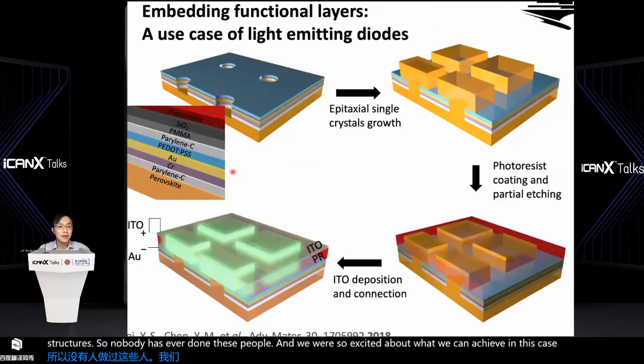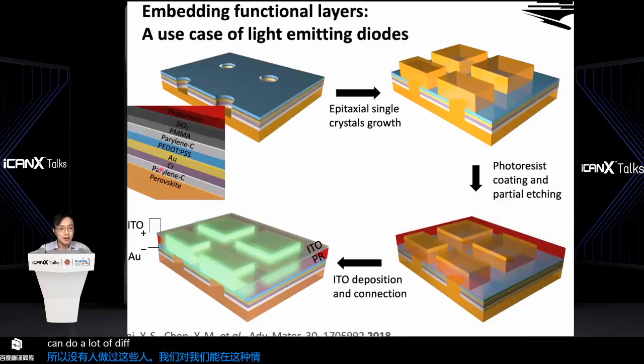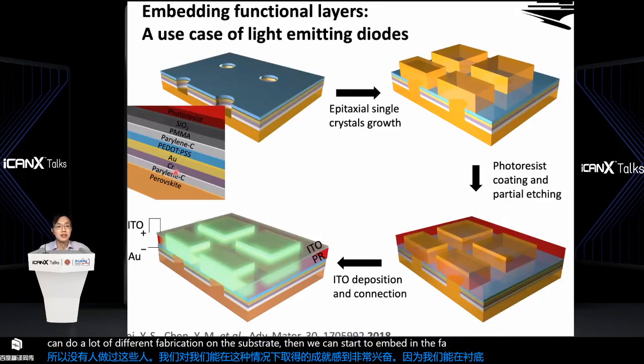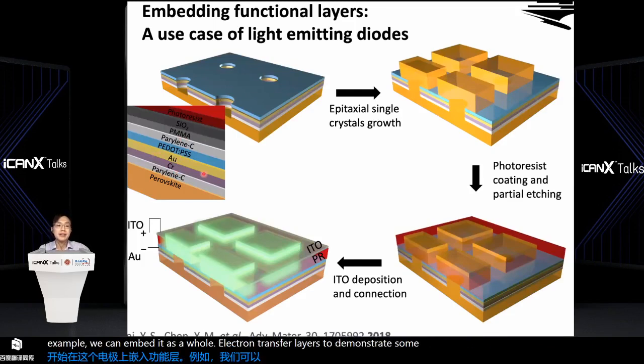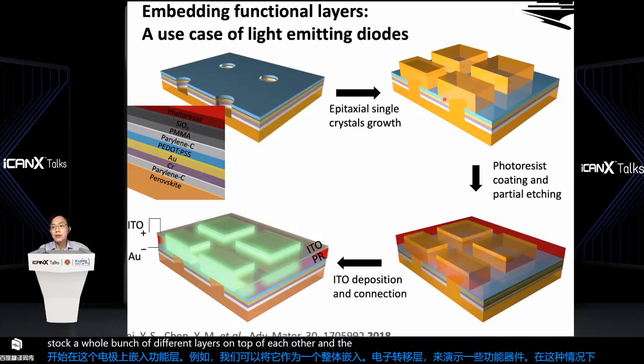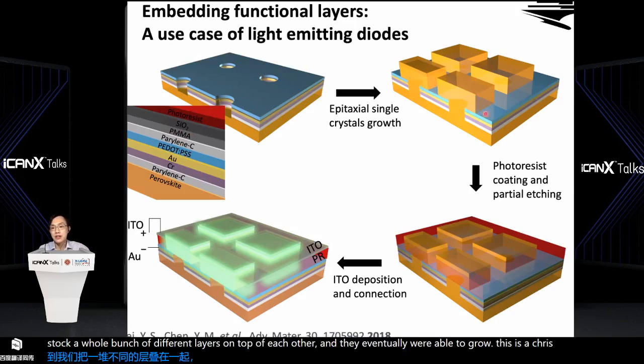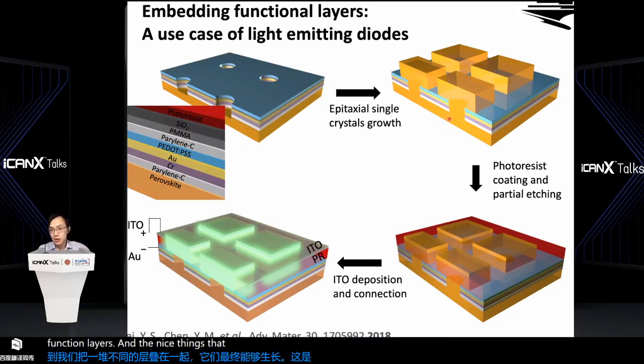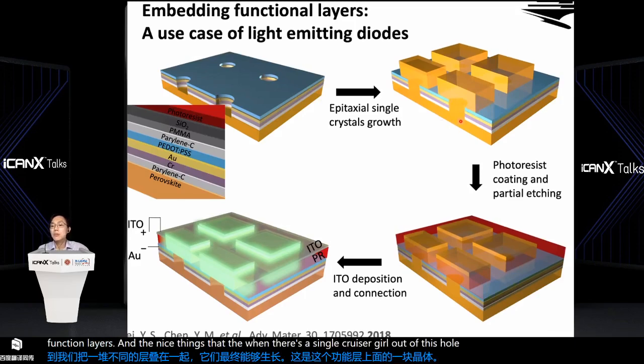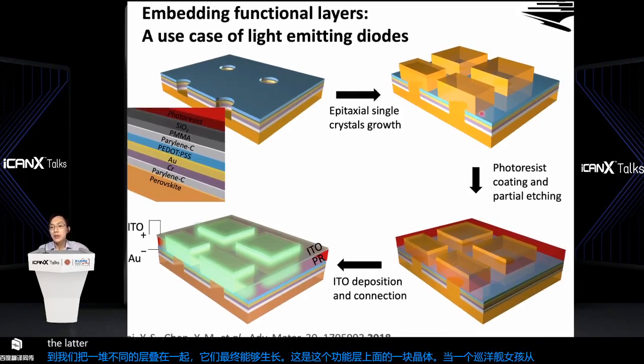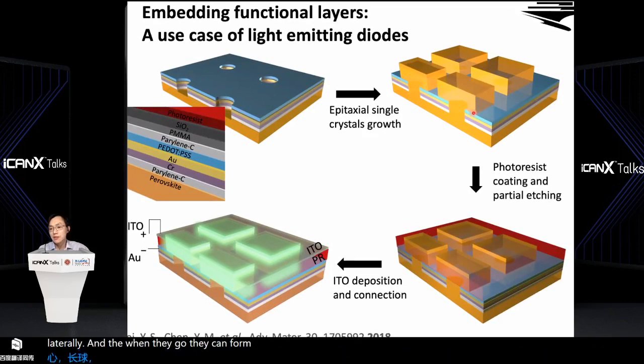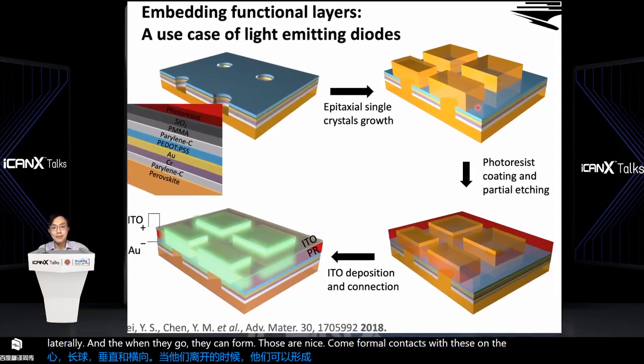And because we can do a lot of different fabrication on this substrate, we can start to embed the functional layers on top of this electrode. So for example, we can embed hole and electron transport layers to demonstrate a functional device. In this case, you can see we stack a whole bunch of different layers on top of each other, and eventually we're able to grow this crystal on top of these functional layers. And the nice thing is that when these single crystals grow out of these holes, they can grow both vertically and laterally. And when they grow laterally, they can form nice conformal contacts with the underlying functional layers.